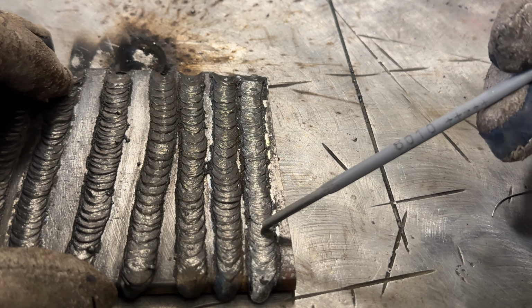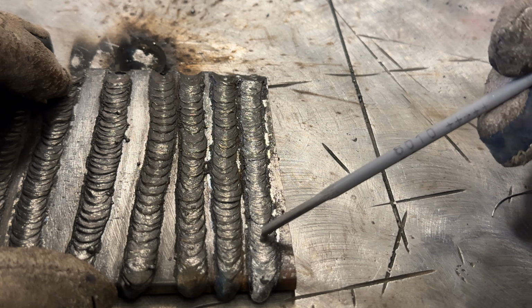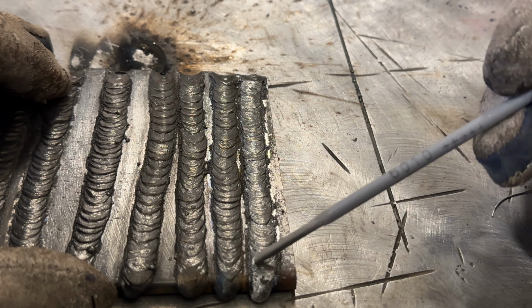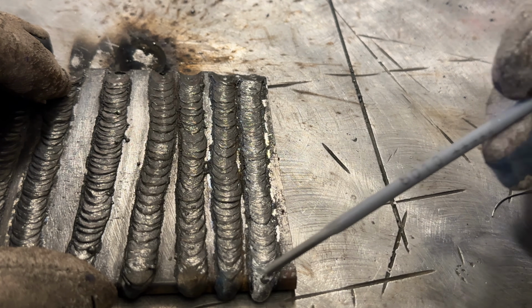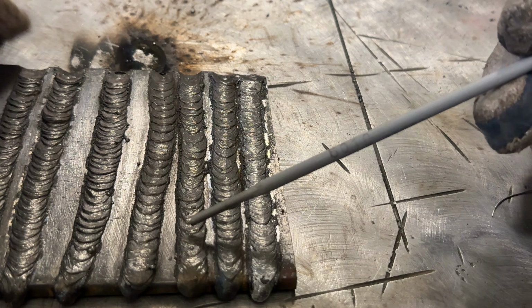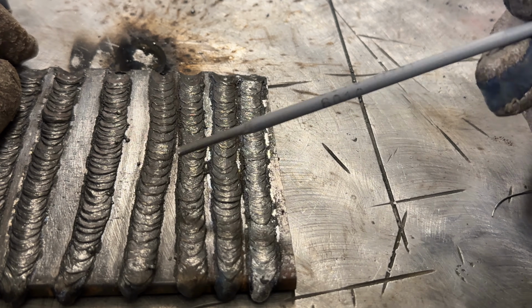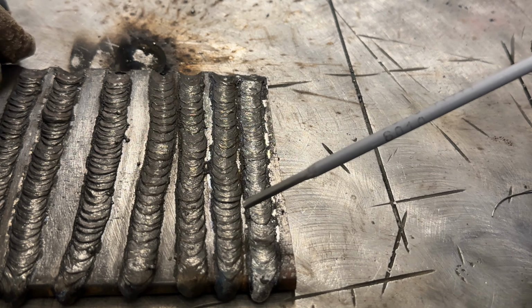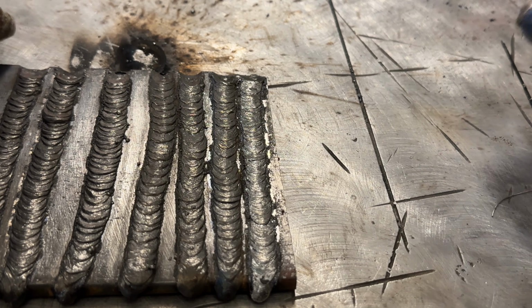As I moved and stitched forward a little bit, that weld pool was staying liquid far behind the rod, and I'm sure if you paid attention in the video you would have seen that. And I'll even put a comparison up right now so you can see what I'm talking about. 5P red rod is on the left and 5P plus is on the right. You can see how much more liquidy that puddle is on the right with the 5P plus versus the left. The puddle pretty much stays right on that red rod.